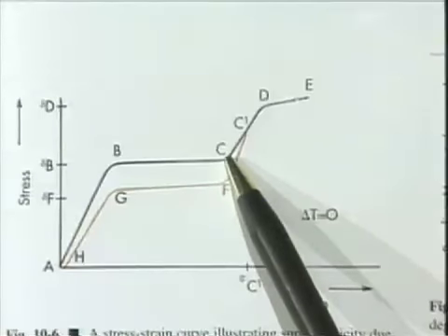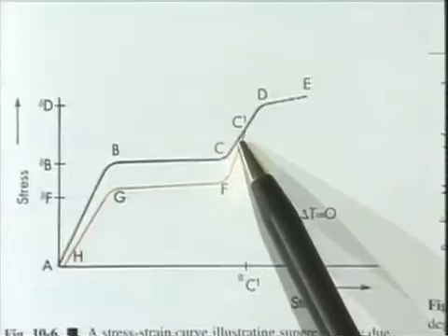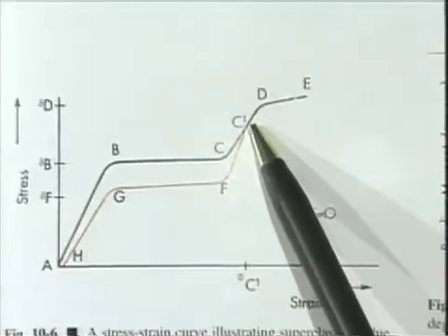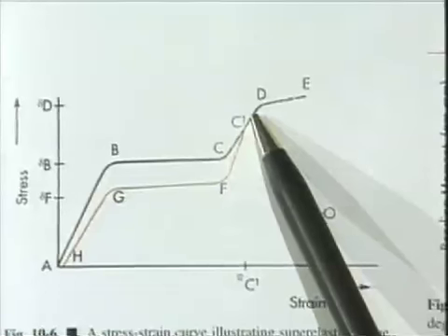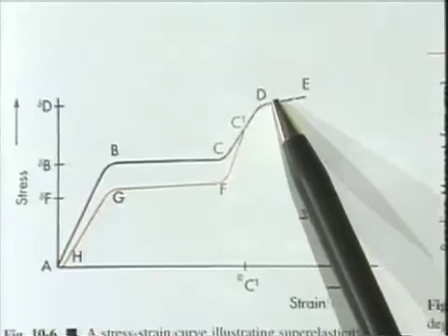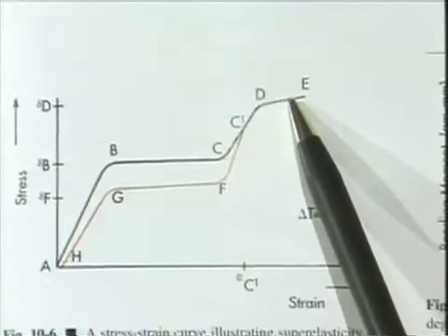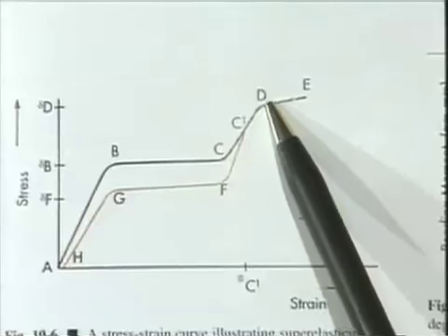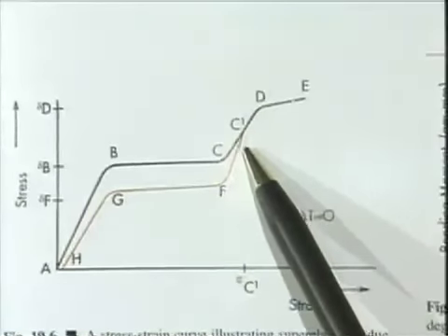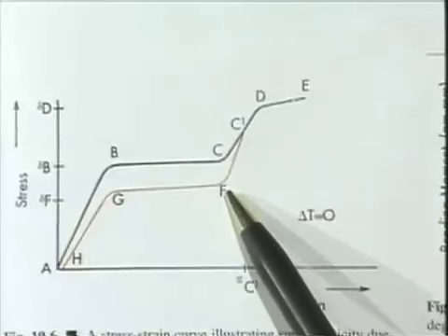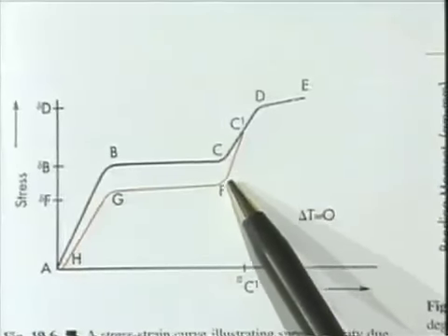At point C over here, all the austenite has become martensite. And now we're looking again at a portion of a curve that looks just like that traditional force deflection or stress strain diagram. It's got a shoulder. Right here, far enough, it would break. If we let it straighten itself out, it does another interesting trick, and that is it doesn't retrace its steps along that original curve.